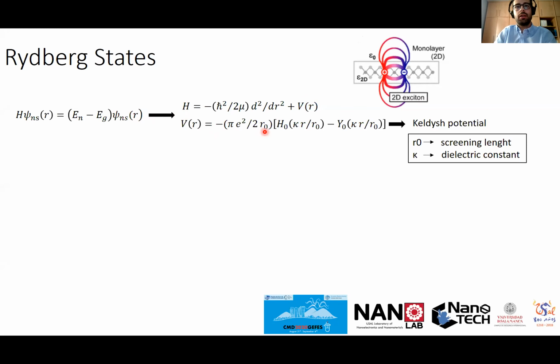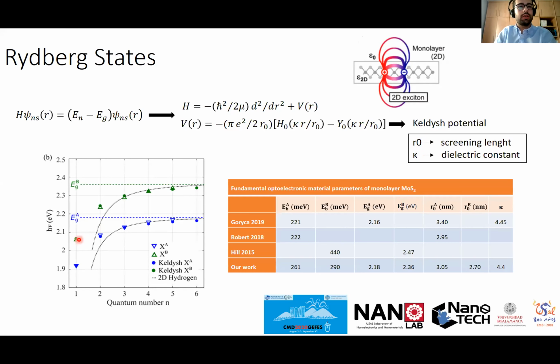This Keldysh potential allows us to solve in a very correct way the different states, and we don't use a normal Coulomb potential because for the excitons in 2D materials the electric field is very screened because of the environment of the phototransistor. So using this screened potential and these parameters, the screening length and the dielectric constant, we are able to perform a very good correlation between the theory and the experiments.